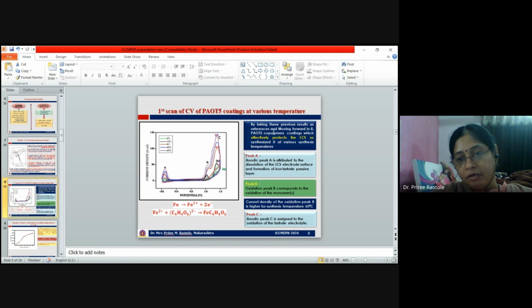So by taking these previous results as a reference and moving forward, the PaOT5 copolymer coatings, which effectively protect the LCS, were synthesized at different synthesis temperatures like 60 degrees Celsius, 40 degrees Celsius, room temperature, 15 degrees Celsius and 0 degrees Celsius.